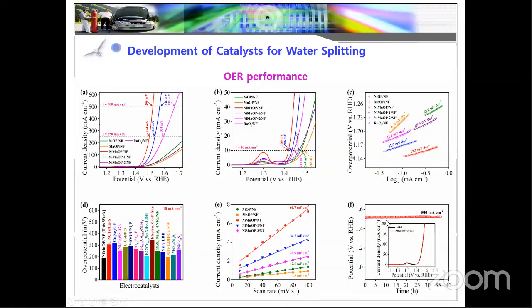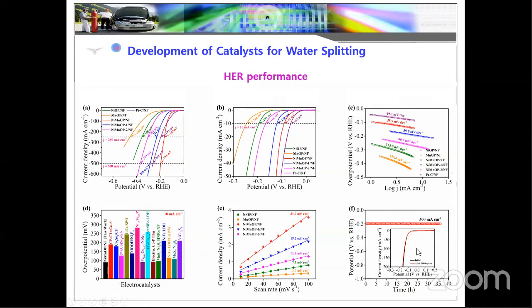We also confirmed the stability. We run stability with chronopotentiometric techniques at high current density. Usually most reports use 10 milliamperes as well as 100, but we are reporting higher current density. Stability is one of the challenges, and we also achieved high current density. Our material is highly stable, and this is further proved by 5000 cycles. Before and after 5000 cycles, you can see the overpotential does not change. The same potential is observed after long-term stability.